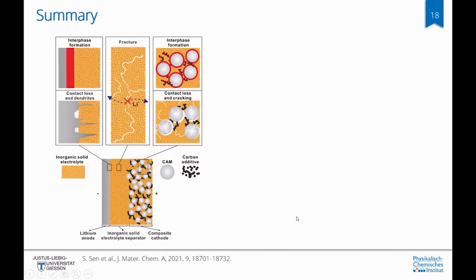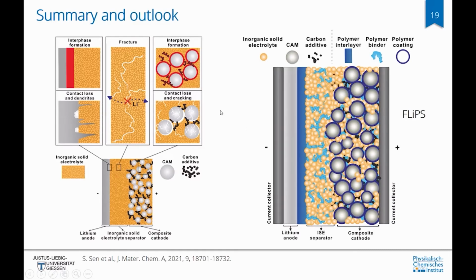In summary, we have investigated the different forms of cell deterioration that can happen in a solid-state battery, to be the interface formation at the anode, dendrite formation, contact loss, and equally fracturing of the cathode and contact loss and interface formation at the cathode active material, and propose as a view to the future that polymers can play a big role at these interfaces and as binders.